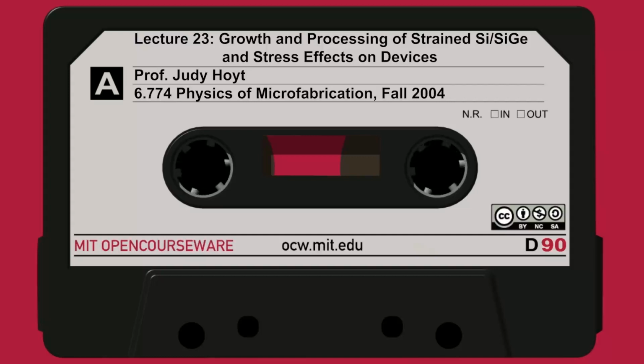And what I want to end up with is there's another approach. People thought, well, why don't you just transfer the strained silicon layer itself? Why do you even have to transfer the silicon germanium? Once you grow the relaxed silicon germanium, you can grow strained silicon on top of it, bond that to oxide, and then remove everything except the strained silicon. And if the strain remains, then you have strained silicon directly on the insulator. You remove the silicon germanium completely. So you don't have to worry about silicon germanium diffusion and diffusion of dopants into silicon germanium and all of that. So this is an ultra-thin strained silicon directly on insulator sort of concept.